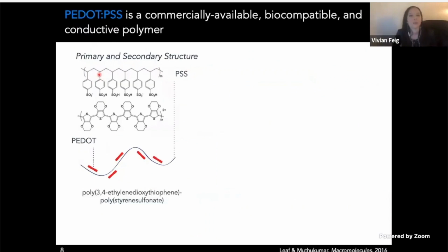And so the way we do that is by working with a conjugated polymer system called PEDOT:PSS, which is probably one of the most commonly used conducting polymers in the biomedical space because, first of all, it's commercially available with really good reproducible qualities. It has demonstrated biocompatibility, and it has relatively high conductivities compared to other conjugated polymers.